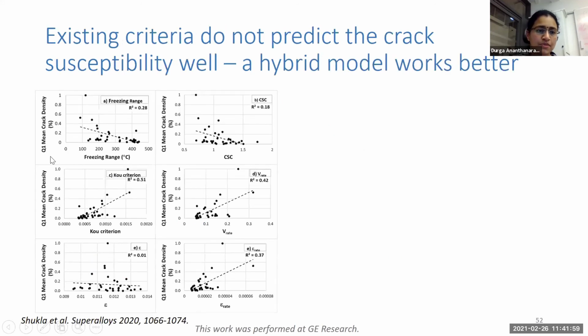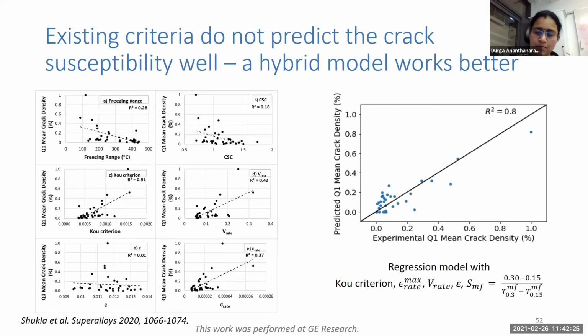What we found was that when we compared the mean crack density measured from the experiments to all of these different criteria, there was actually not very good correlation for any of them. Among all of this, I think the Kou criterion probably performs the best, but even that is not so good at all. So in this case, we tried a different hybrid approach. Apart from this bunch of different criteria, we also took some other related criteria and tried to evaluate which of them has a maximum effect on the mean crack density.